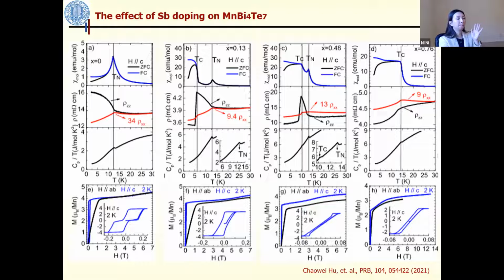The X-ray pattern always had some distortion of the Bragg peak, right? And then for neutron scattering, for the pure 124 and 147, if you put antisites in the refinement, it won't give you anything. It is within the measurement error bar of this neutron instrument, HB3A.